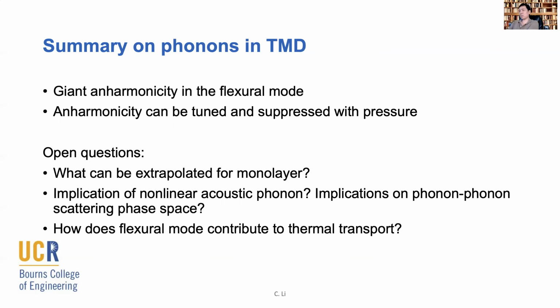But on the other hand, since those phonons have very low acoustic phonon group velocity, that adds a limiting factor on how much heat can be transported. Those are soft phonon modes still. And those nonlinear acoustic phonon dispersions could really complicate the phonon scattering phase space, which is another major factor in determining thermal transport. So we're still trying to figure out if we have a better understanding of how this could cause some exotic phonon dynamics, and that might be quite exciting to understand.